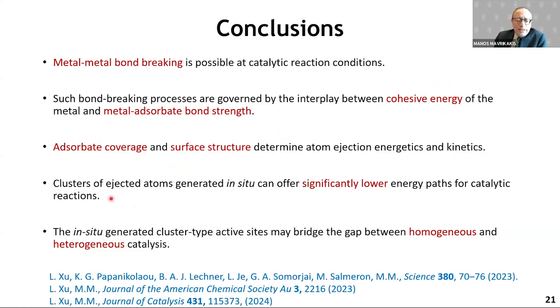We demonstrated that clusters of ejected atoms generated in situ under reaction conditions generate new reactive intermediates with significantly lower energy paths for catalytic reactions, that would lead to complete reconsideration of several of these very important, practically important reactions. And finally, for more scientifically inclined people, there is always the so-called heterogeneous-homogeneous catalysis gap.